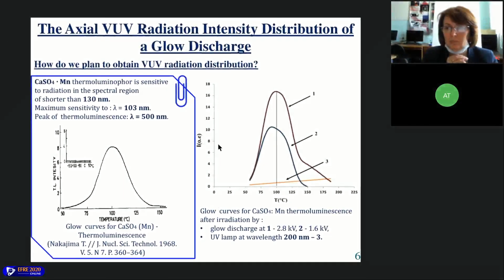Sorry, next slide, slide number 6. So how do we plan to obtain the vacuum ultraviolet radiation distribution? In order to answer the question, we carried out experiments with synthesized calcium sulfate with manganese, a thermoluminescent material sensitive to radiation in the spectral region shorter than 130 nanometers. And some details about this material you can see in this frame. We synthesized this material, and on the right of the slide you can see glow curves. This material glows after irradiation by glow discharge at different voltages, and in order to check that our material is not sensitive to wavelengths at, for example, 200 nanometers, we carried it out too, and we see there are no glow curves.